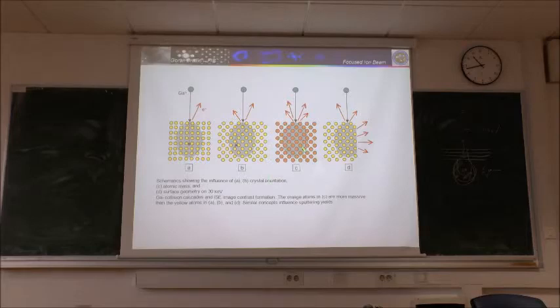or the atomic number. So if you have heavier elements, gold, platinum, compared to aluminium or carbon and so on, at higher Z materials we will have higher signals. And also important is the angle, what we explained before. In this part the angle could be practically 90, and this part is 0. So from this part we'll get more information, more electrons and ions, than from that part here.